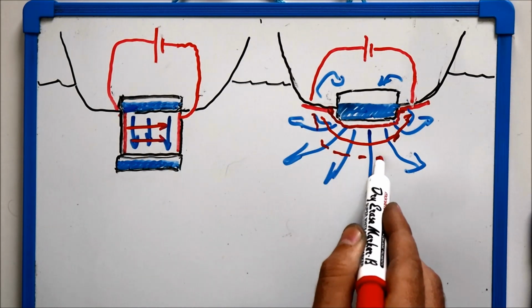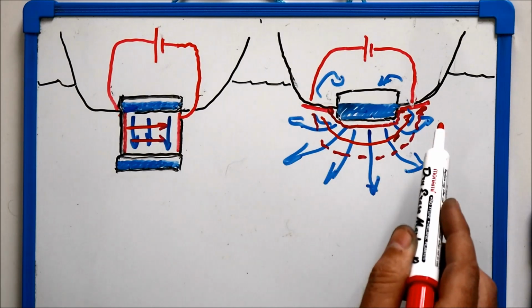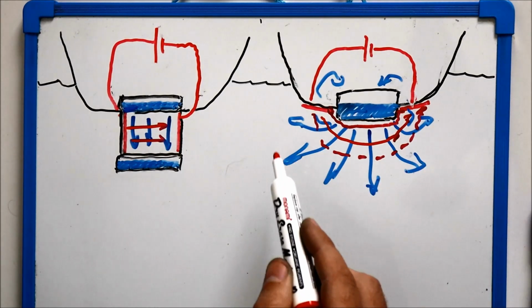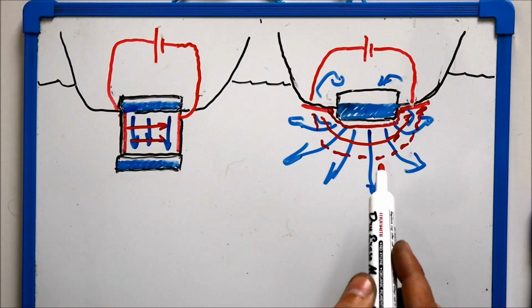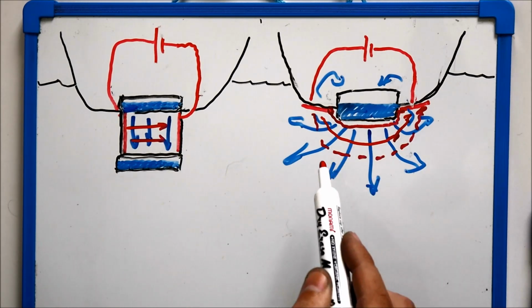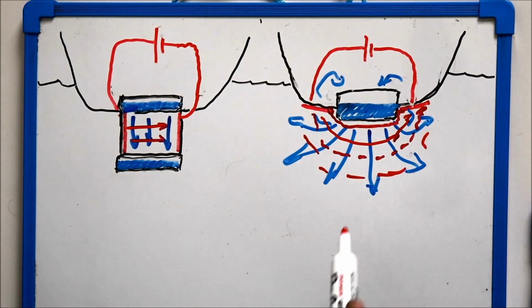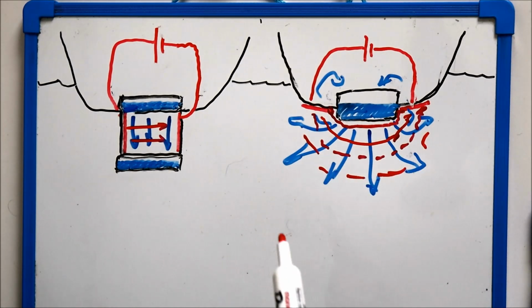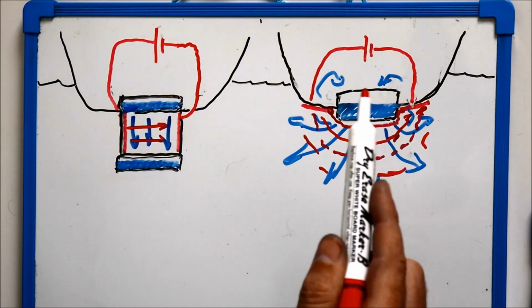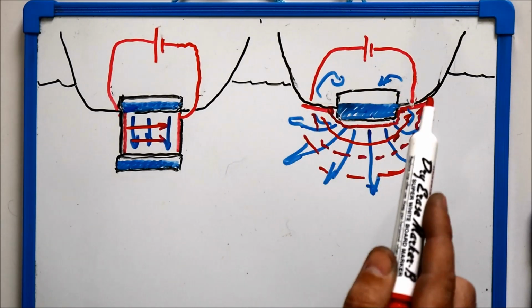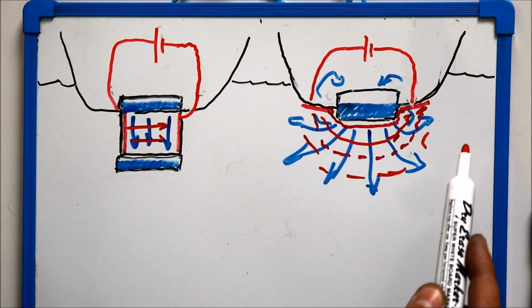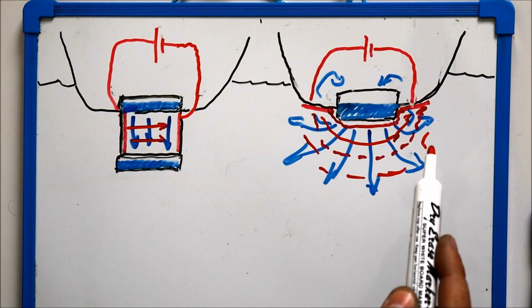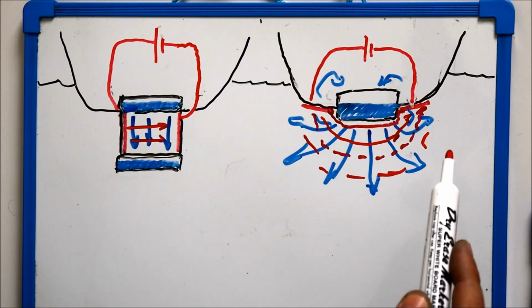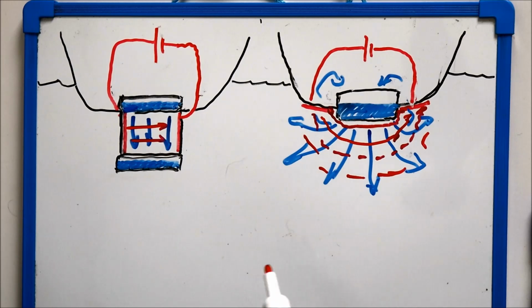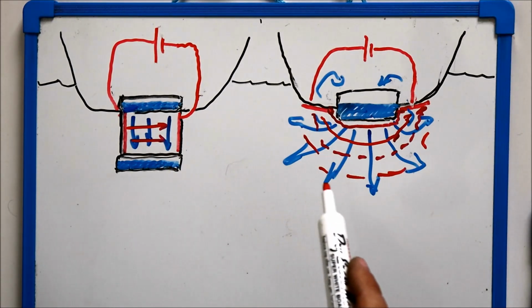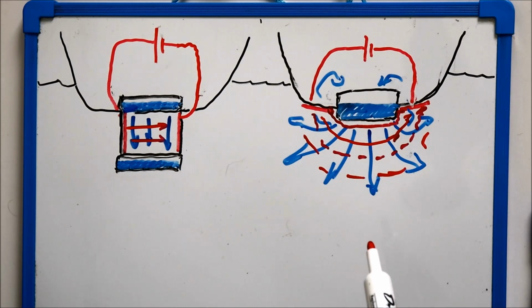Whatever current flows further away, the longer path through the water means higher resistance, and for a given voltage that would mean a reduced current. However, I'm pretty sure that we do have current flowing rather far from the magnet, purely from observation. I tested the setup for current flow in a shallow tub, say about a centimeter or two deep in salt water, and the current was about half of that compared to the current through deeper water. There's definitely additional current flowing through the deeper parts of the water.